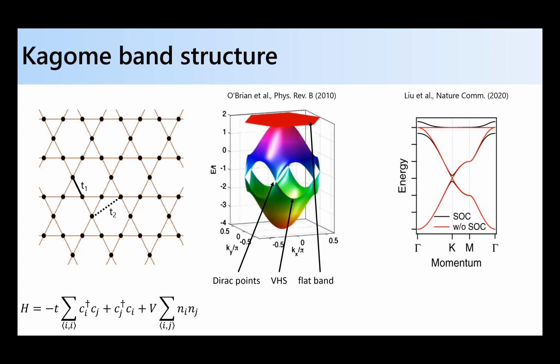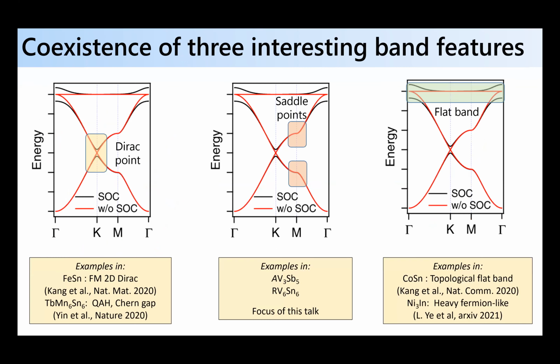If you cut along high symmetry directions here, you can see the Dirac points at the so-called K point in the Brillouin zone, these two saddle points at the M points, and then the flat band feature. This is interesting because one can potentially engineer electronic states that sample topological and non-trivial types of electronic features, as well as correlation effects that can be engineered by increasing the density of states, by tuning the band filling to the flat band, or potentially near these saddle points, which also form Van Hove singularities.